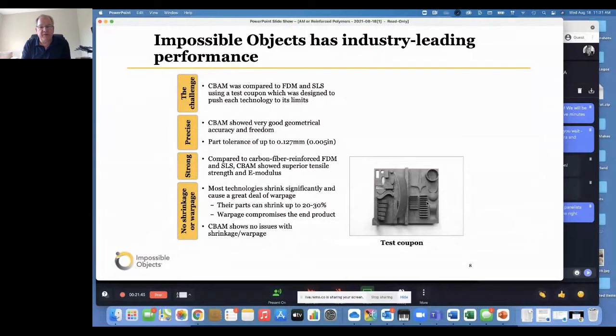One of the interesting things is that when you compare this to powder bed systems with smaller fibers under 1 millimeter in length, or extrusion-based systems, usually under 0.5 millimeter in length, those are going to give you a little bit of a performance gain in strength, electrical, and thermal properties. But the real advantage with this particular process is that we're forming the parts under pressure and temperature in that heated press, and therefore the warpage and curl issues that you typically see with some of the other additive processes don't show up. Having said that, you get really nice surface finish and pretty good part tolerances: 0.005 of an inch, or 0.127 millimeters, is the overall tolerance that we've measured to date. But it's the warpage and shrinkage issues that are controlled and well maintained in this process. Last slide, please.